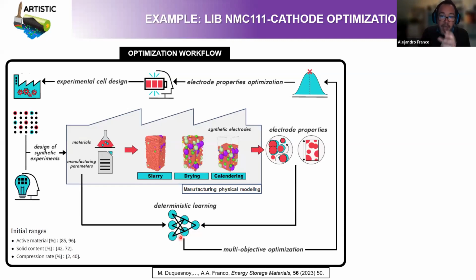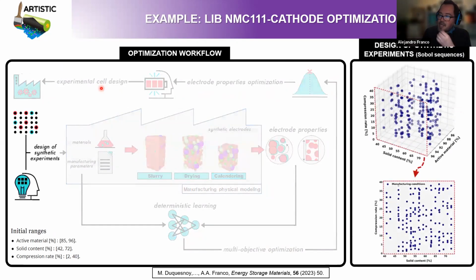And then we embed it in a multi-objective optimization algorithm based on a Bayesian optimization technique in order to predict which are the parameters you need to adopt in the manufacturing process in order to reach electrodes with optimized properties. This is a detail of how we are actually designing these synthetic experiments, right? We use a technique called Sobol sequences. That means that these synthetic experimental points are taken randomly between these three variables that we have explored here. Once again, solid content of the slurry, formulation of the slurry, and compression degree upon calendering.